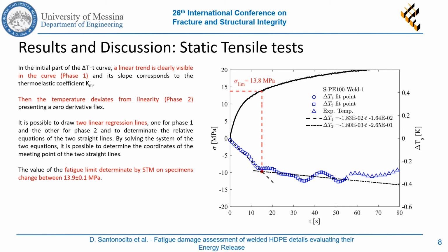In the initial part of the temperature-time curve, it is possible to clearly distinguish the linear trend of the temperature, then it deviates from the linearity, reaching a plateau region. It is possible to draw two linear regression lines, the former for the first linear phase and the latter for the second phase, not taking into account the temperature values near the slope change. Solving the system of equations, it is possible to determine the intersection point of the two straight lines.